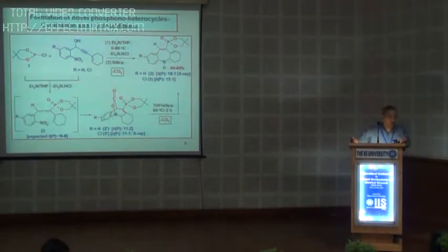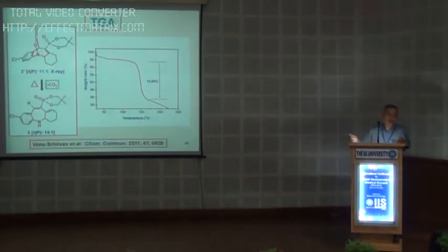Sometimes there may be bubbling, okay? And in this particular case, there was bubbling which the student noticed. Therefore, I asked him to prove the elimination of carbon dioxide by some other means, and that is what is shown here. You see that if you take TGA, elimination of carbon dioxide can be readily noticed there. The weight loss corresponds exactly to the elimination of carbon dioxide. So that is something which can be done when you want to explore things and find out what is happening in the reaction mixture, if you are carefully observing the reaction or the compound.